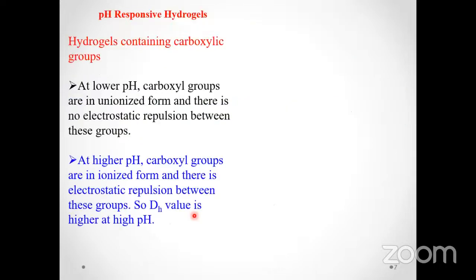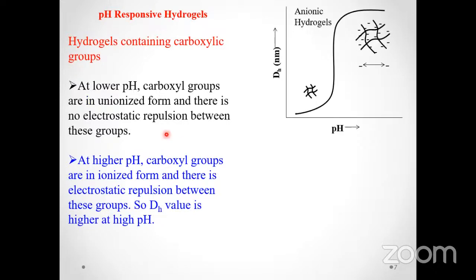For example, here are the pH responsive hydrogels. Hydrogels containing acidic or basic functional groups can respond to the pH of the external medium. For example, if we have a hydrogel containing carboxylic groups, which are acidic in nature, then at low pH value, the size of the hydrogel particle will be smaller, and the smaller size is due to the protonation of the acidic functional groups. But as we increase the pH of the medium, this results in the deprotonation of acidic functional groups on the hydrogel, and negative charges are created if carboxylic groups are present in the structure. These negative charges will repel each other, and this will result in the extension of the polymer chains.